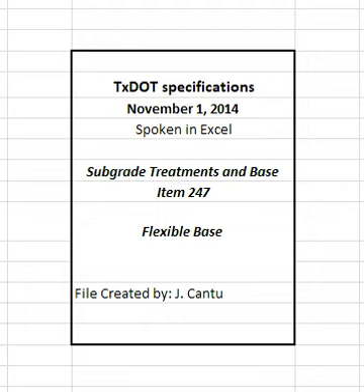For RAP, do not exceed a maximum percent loss from decantation of 5% when tested in accordance with TEX 406A. Test RAP without removing the asphalt.